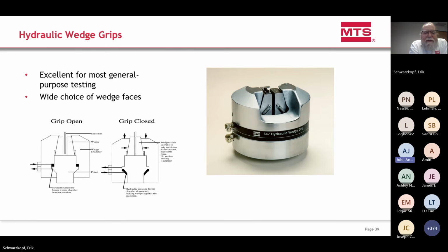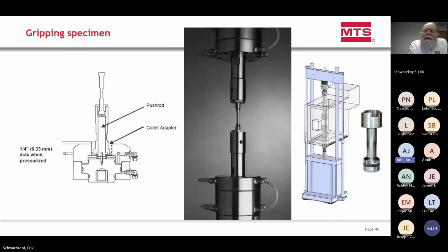Some of the grips MTS sells, the most common, are hydraulic grips, which allow loading in tension and compression of the specimen without any slop going through zero. But you need a different kind of grip for aggressive environments, so there are various grips that allow that compression and tension through-zero loading required by strain control fatigue inside a furnace, where the oil for hydraulic grips can't go.